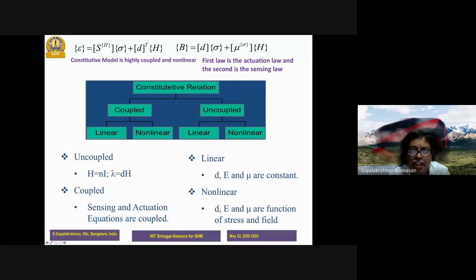So these are highly coupled. When you change H, the strain changes; when the strain changes, the stress changes; and when the stress changes, the permeability changes. So you just cannot uncouple this equation. That is where most people use an uncoupled equation. When they uncouple it, they say that the magnetic field is directly proportional to current, using the number of coils here. And this is a kind of wrong assumption.